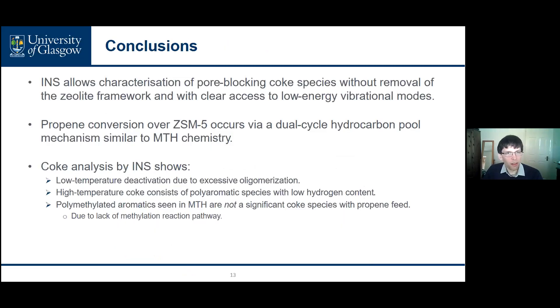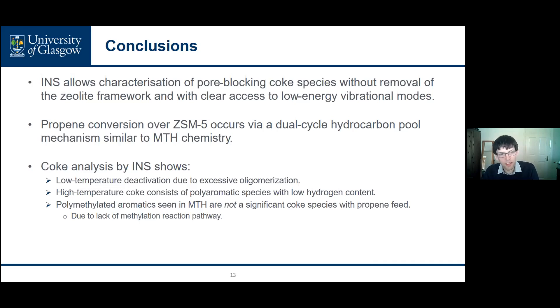To summarize the conclusions: we successfully used INS to characterize pore-blocking coke species in the reaction of propene over ZSM-5, which is the first time it has been applied to reactions of olefins in this fashion. We confirmed that propene conversion occurs via a dual cycle hydrocarbon pool mechanism, quite similar to methanol to hydrocarbons chemistry. INS analysis of the coke species shows that deactivation at low temperatures is due to excessive oligomerization reactions. The high temperature coke consists of polyaromatic species with extremely low hydrogen content, and polymethylated aromatics produced in methanol to hydrocarbons chemistry are not a significant coke species with propene feed, due to a lack of a plausible methylation reaction pathway to form them.